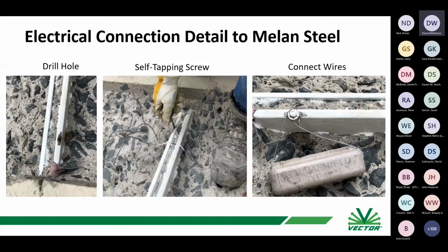The anodes need to be electrically connected to the steel in order to work, okay? And so normally for normal rebar, the typical connection detail is just you clean the steel, you wrap the wires around and you twist them tight, just like you would for tying rebar together. Because we're dealing with steel angles that are embedded, and in most cases still partially embedded in the concrete, it's not really a practical way to make an electrical connection to them.